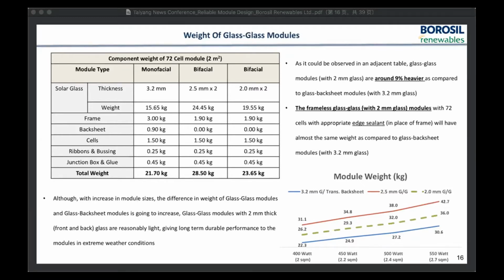So this difference could be eliminated. Here the module typically has a frame, which is of the order of 2 kgs. So if we eliminate the frame altogether and use a proper edge sealant, then the weights are all at par. So a bifacial module with 2 mm thick glass on both sides and a frameless design with a proper edge sealant, which will ultimately last till the contract period or the module life, will have no issue of weight. Otherwise, if we keep adding 2.5 mm glass, a lot of weight will be added.